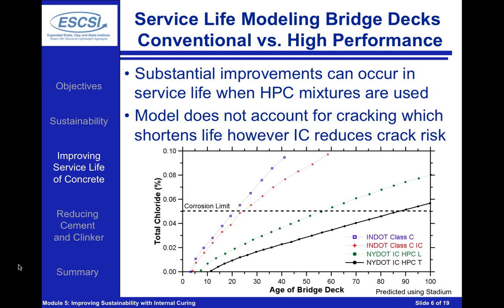And what we can see is by moving from a conventional concrete, which was shown in that blue line, to a higher performance concrete with a lower water to cement ratio and the addition of supplementary materials, we can start to extend the time to corrosion from 20 to, let's say, 55 to 80 or so years. And by using internal curing, we can dramatically reduce the potential for cracking, which is really the Achilles heel of these high-performance concrete mixtures.